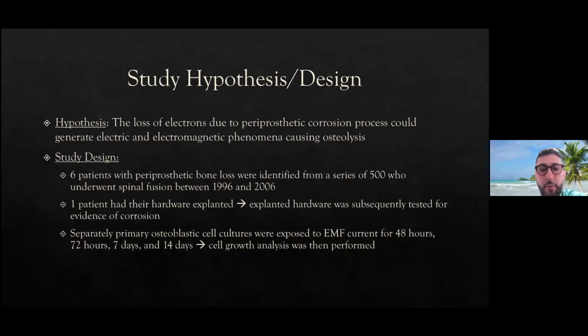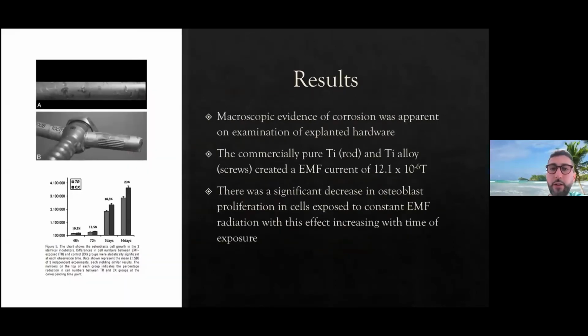And then they separately prepared osteoblastic cell cultures, which they then exposed to the EMF current that was actually produced by this hardware. First off, they did find macroscopic evidence of corrosion. A lot of the corrosion was fretting that you can see here, which is a mechanical corrosion. And they did find a current, and I've put the current here. Obviously the current was created because the rod itself was commercially pure titanium and the screw was titanium alloy, so there was some electrochemical difference.